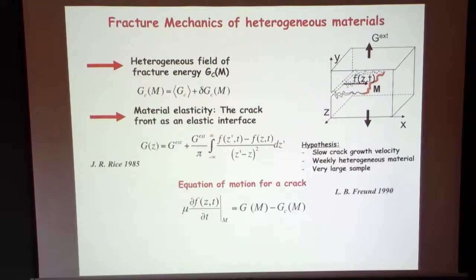You might think this is a quasi-static approximation, but under the right conditions, and if you're really interested, we could go into a long discussion of what the right conditions are, basically a crack will instantaneously, at least in this theory, adapt to whatever the driving is at the point. Now, why is it massless? It's basically because the information propagates away from the crack faster than the crack can move. It's limited by the wave speeds of the material, so it never can interact with itself if it's a large enough medium. But the equation for G is assuming an instantaneous propagator.